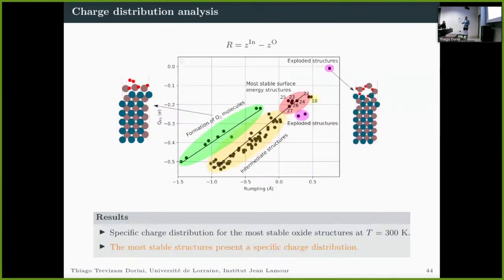In addition, we have also studied the charge distribution of all these phases. On the left, we have the Bader charge analysis on the palladium atoms in the last layer that is in contact with the oxide, against the rumpling, which, as a reminder, is the difference in height between, in this case, the indium and oxygen atoms. It's interesting to see that we can separate these structures into 4 different categories. The first one includes structures in which there was the formation of O2 molecules, as you can see here. The second one, the purple one, is where some structures, as I said, exploded. That's basically where the oxide has some atoms that are not in contact with the substrate anymore.